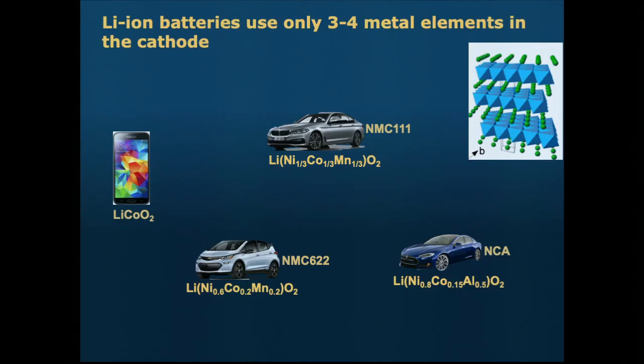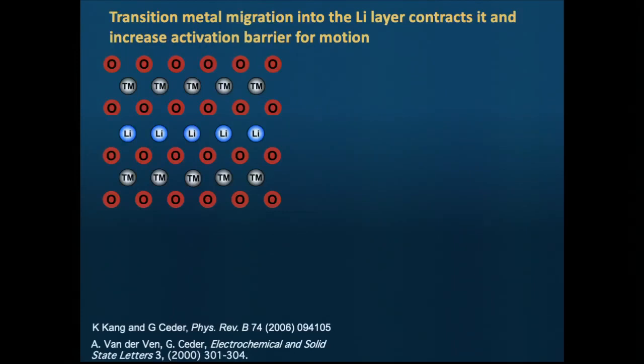So the fundamental question that we asked ourselves is, why after 30 years of cathode research are we limited to three elements? And that's an interesting story. It turns out it's a very fundamental piece of physics. If you take a layered cathode, and I made a cartoon here, when you charge the battery, you extract lithium, right? And what happens in many materials is that you've got an enormous amount of vacancies. We pull out as much as 75% of the lithium. So you create all these vacancies, and in many cases these transition metals will migrate in there because they have to make only a single atomic hop to get in there.